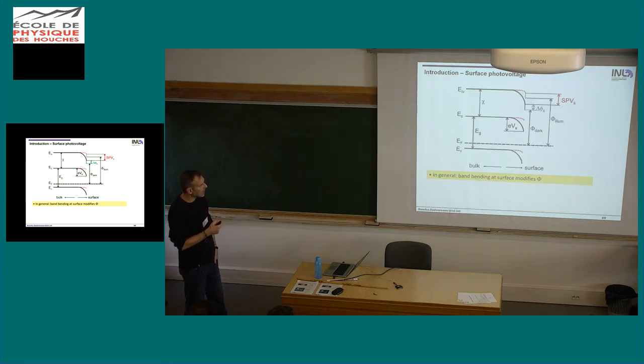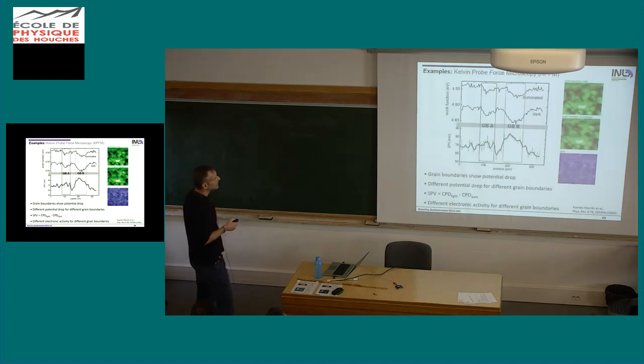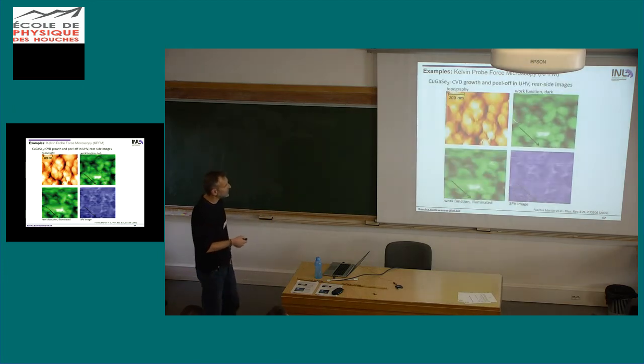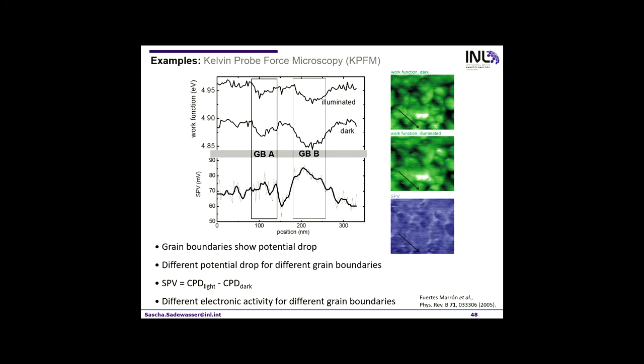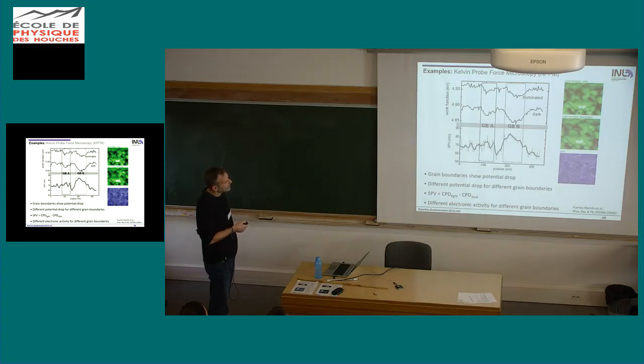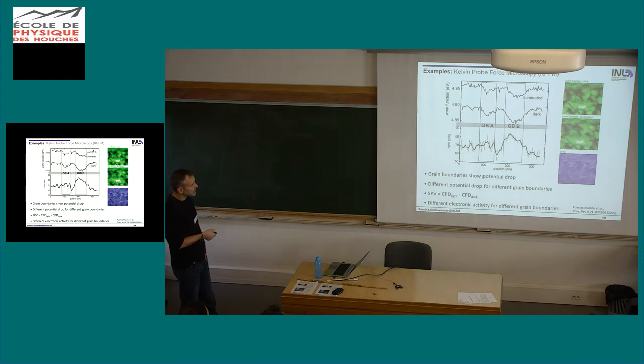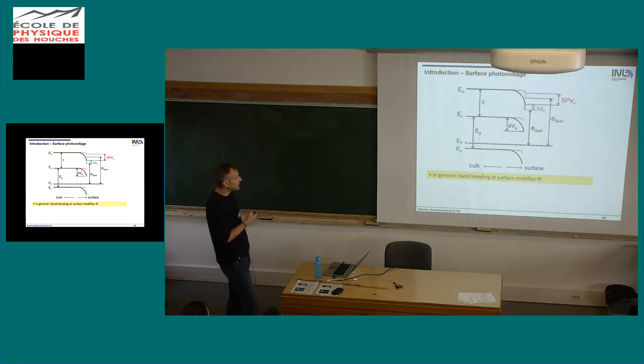So now with this small introduction, I will go back. Sorry about that. If we look again carefully at this, what we did on one hand is we just subtracted these two images, and then we get the surface photovoltage image. For this you have to be very sure that the two images are very well aligned. And we see these white lines here. If we go again to this line scan and look carefully, we see that this drop here is more or less the same, whereas this one here is smaller under illumination than this one. So there's a change in band bending at the grain boundary due to the illumination. And you can see here that this actually appears slightly white. Sorry, I forgot to say that the surface photovoltage is the contact potential difference under illumination minus that in the dark.